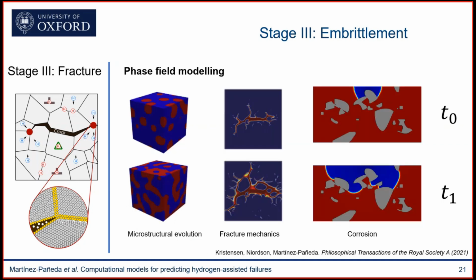And I mean, phase field modeling has been a revolution in many areas of science and engineering. It all started in the condensed matter physics community, where it's now by far the most widely used technique to simulate microstructural evolution. It has very quickly become the dominant tool also in fracture mechanics. And we have recently shown that this paradigm can also be extended to corrosion. So you can use these phase field models to describe the evolution of the corrosion front, the interface between the aqueous electrolyte and the metal, and therefore resolve the physical processes involved in corrosion.